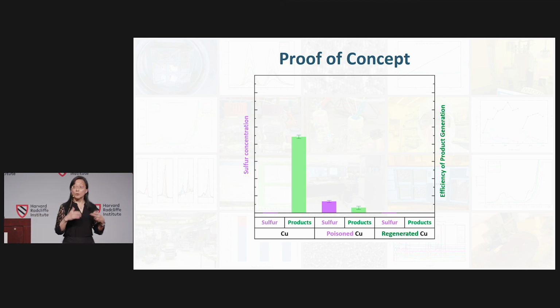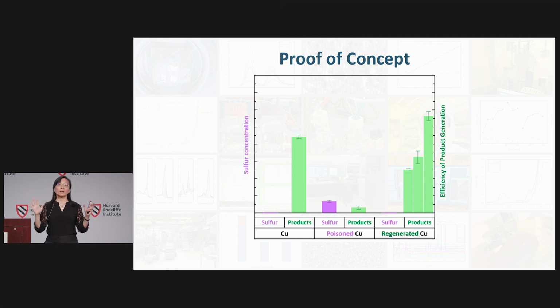Now, we treated the surface with our atomic layer etch processes. I'm going to show you 3 sets of data because they are interesting in their own ways. The reason why they are different is because we tweaked the process conditions that we used. But here is the data as a group. I want you to first look at the data and agree that compared to the poisoned surface, we recovered the catalytic activity. Maybe we didn't always recover it fully, but we recovered the catalytic activity. So that is good. Why are they not the same?